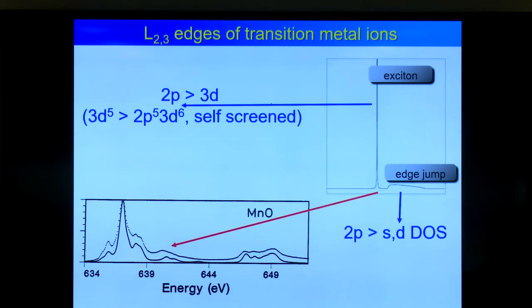And the reason it works is that it's a completely self-screened experiment. When you excite a 2p electron to a 3d electron, the 3d electron is still localized. So everything around the manganese doesn't even notice that something is happening. So it's really a local excitonic transition. I'm going to discuss that now a little bit more in detail because that comes back for the K-edges, metal K-edges.